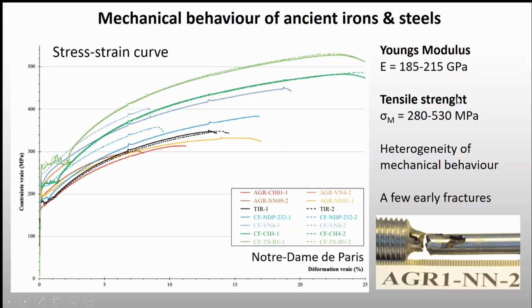On the other hand, the tensile strength has much difference, and the cresting, especially the two curves in green, which are the 20th century iron, have good properties, whereas the others, and even the TIR-1 from the 19th century, have much poorer mechanical properties, which are just around 300 MPa. This is really low compared to modern alloys, of course, but is actually normal for ancient iron before the end of the 19th century.